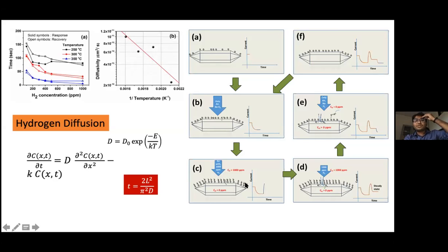Once sufficient hydrogen saturation has happened on the surface, a hydrogen concentration gradient develops. There is a large concentration of hydrogen on the surface, and there is zero concentration of hydrogen inside the lattice. That concentration gradient drives diffusion of hydrogen inside the lattice, and this hydrogen diffusion reduces to some extent the surface adsorbed hydrogen, which leads to a reduction in the current. Again a steady state is reached. There is an equilibrium, for a given concentration of hydrogen, between incoming hydrogen and outgoing hydrogen.